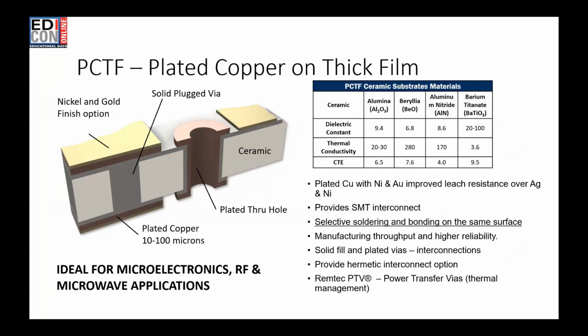And what we can build, or we can drill holes into that, either laser drill or mechanically do it. We can do the plate, and these holes can be plated through holes, or they can be filled. And if you look at the layers, metallization layers, which are on the top and bottom, they can be selectively plated. So again, we'll start with a seed layer. We'll also deposit copper on it, and then we can open the windows such that you can have copper exposed for soldering purposes. We can plate the gold in the selective areas, and one can do bonding.